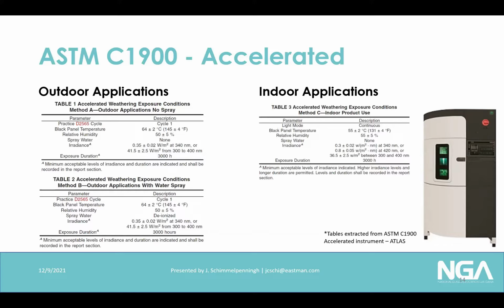If you look at the indoor accelerated method, you'll see that it can be done in the same chamber, but not at the same time. And the reason for that is the temperature is a little bit lower. So you're at about 55 degrees C or 131 F instead of the 145. Your humidity is slightly higher, or sometimes you can have more humidity inside. There is no spray, and you can see the irradiance levels are slightly lower for that. And so those are the two different indoor and outdoor applications.